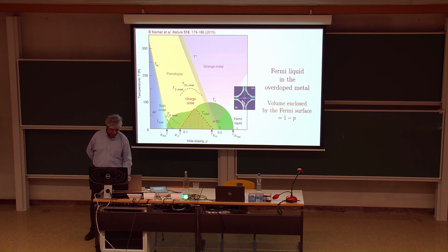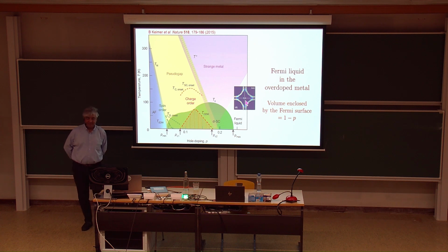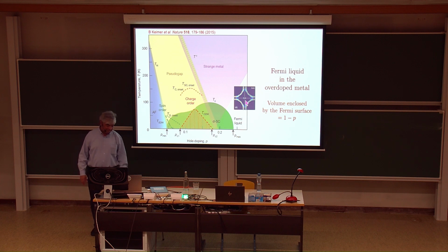Okay, so that's good. Now, in the usual approach to different types of ordering in metals, which has been thoroughly established and very, very successful, you start from the Fermi liquid, and then you look at its instabilities. It can have the BCS instability to superconductivity. It can have charge density wave or spin density wave instabilities. Okay, so you could do that even in these materials, but the first thing you notice is that the place the Fermi liquid appears is where nothing interesting is happening. So really the point number one of my talk is we cannot think of these low temperature phases as instabilities of the Fermi liquid.